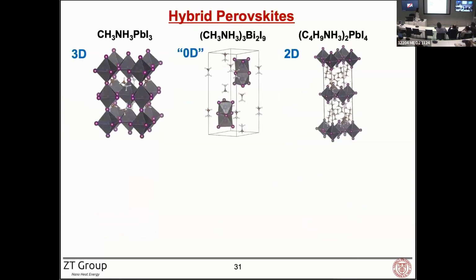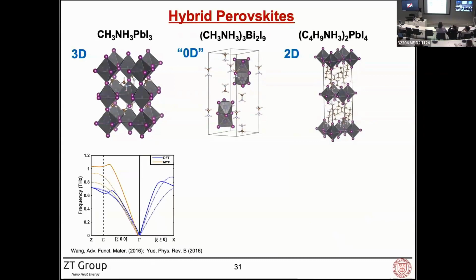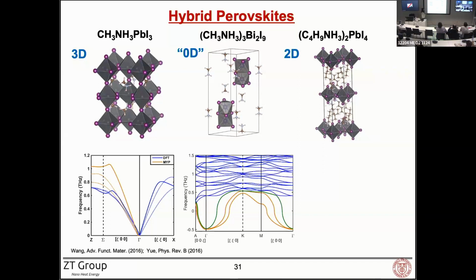And then we looked into the literature, and we identified three hybrid perovskites as representative materials to represent the different dimensionality of the inorganic groups. At that time, when we started this project, the only literature study we could find was these two calculations on methylammonium lead iodide. As you can see, there's a clear difference between those two calculations. And for the other two materials, we didn't find anything. We actually performed the calculation ourselves on the second material, and we saw these very negative frequencies indicating an unstable structure. And so we said, okay, how about we measure the phonon dispersion to provide some benchmark for those materials.